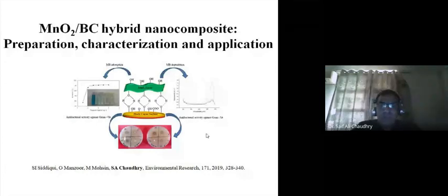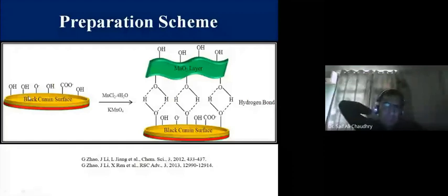Now, for the preparation part, this black cumin or other organic, plant-based materials have a number of functional groups at their site. Here we have shown that OH is one of the groups, and sometimes it is O negative, and other times it is COO negative, meaning an acidic group, and sometimes maybe amide, but we have just ignored that. And now this manganese source MnCl2 was taken and it was oxidized using KMnO4, potassium permanganate solution, and it led to the formation of